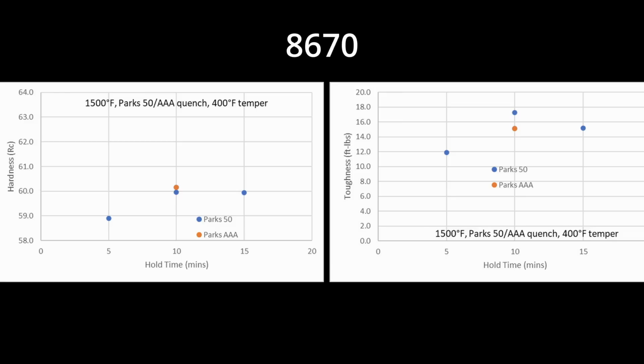The 10 and 15-minute holds had about the same properties. We did not have worse toughness or anything by using the 15-minute hold. So don't be afraid of holding the steel for a few minutes longer than is strictly necessary. Trying to go shorter for improved properties is unlikely to lead to a better result.